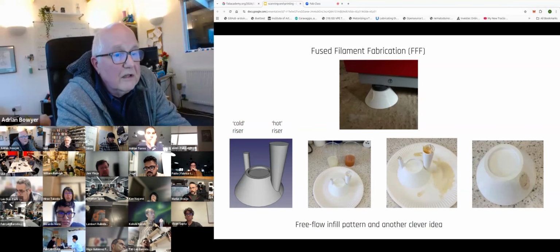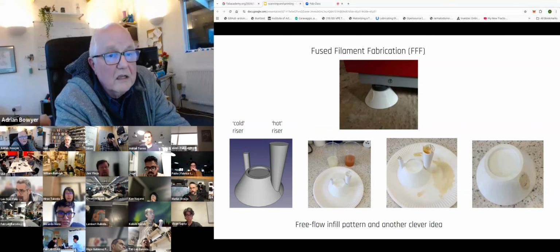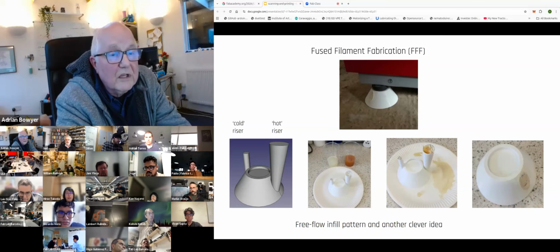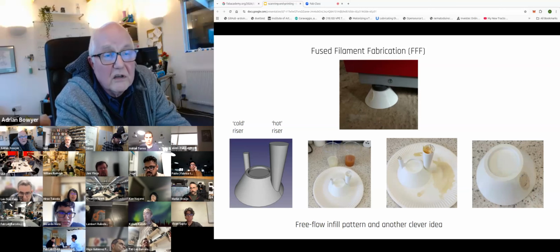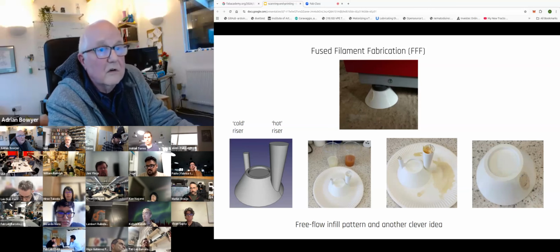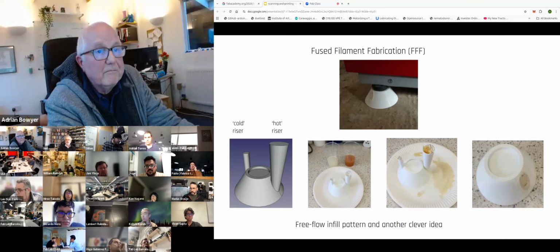If it's that free flow infill, I can mix up some resin, pour it down the hot riser, wait till it sets, cut the risers off, and now I've got a 3D print that was made in an FFF 3D printer, but which is filled with solid resin. And that is, of course, much, much stronger, and indeed strong enough to support the weight of a heat pump.